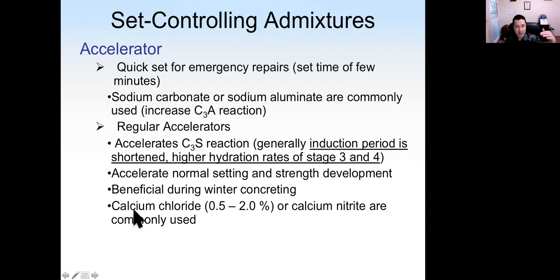So we use regular accelerators in winter concreting. That can ensure the concrete will not be too cold to freeze. Calcium chloride or calcium nitrite. So these calcium salts are normally used.